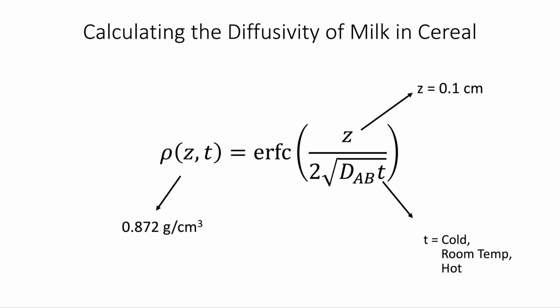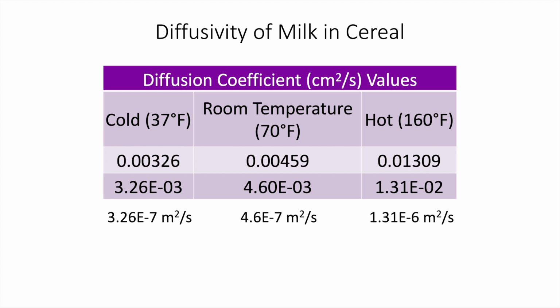So at the cold temperature, there's an average time taken to become saturated. At room temperature, there's an average time for the cornflake to become saturated, and at the hot temperature as well. So once we get all these, we can calculate the diffusivity of milk and cereal at the varying temperatures. And here are those values. At the cold temperature, we have about 3.2 or 3.3 times 10 to the minus 3 centimeters squared per second. At room temperature it is about 4.6 times 10 to the minus 3. And for the hot cereal in cornflakes, it's about 1.31 times 10 to the minus 2.